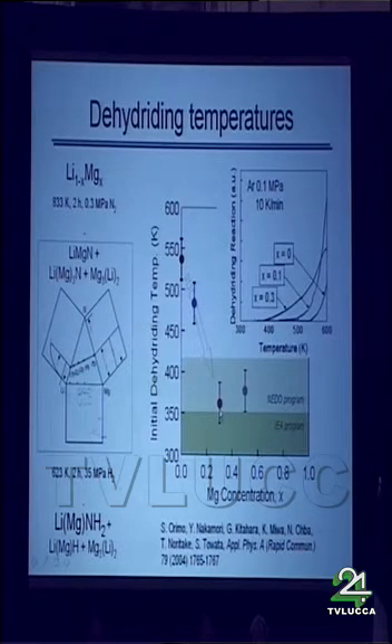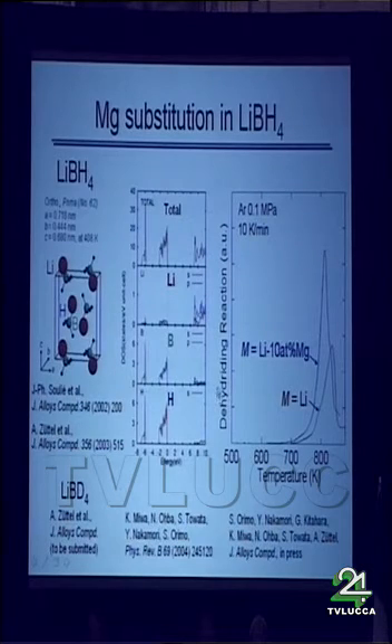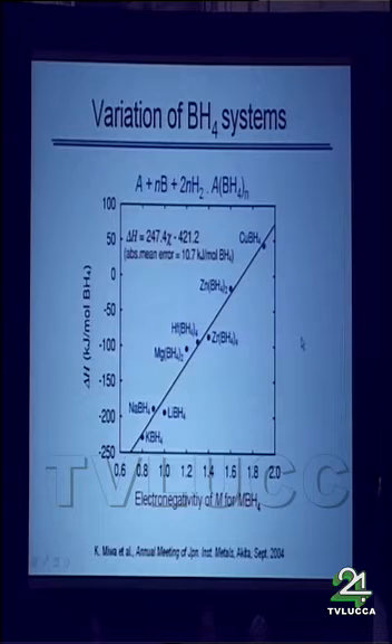This technique was also applicable for the borohydride system because electronegativity is also important there. Again, the electronic structure is similar, I mean the same as that for the amide system. And here's the result, without substitution and with substitution, where just 10% of the cation was substituted by magnesium. I'm not trying to increase the amount of substitution. Again, considering the electronegativity is important, or sometimes indispensable, to widely open the possibility of complex hydrides for hydrogen storage materials, especially the borohydride system like this.